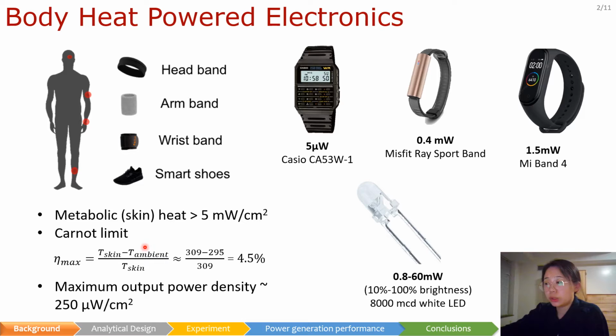According to Carnot's rule, the maximum efficiency is the ratio of the temperature difference between the reservoirs to the hot reservoir temperature. Therefore, we can estimate the maximum output power density of a device operating between the body temperature and ambient temperature to be about 250 microwatts per square centimeter. Given that the power demand of most IoT devices, as you can see examples on the right, is on the order of microwatts to milliwatts, we believe proper utilization of human metabolic heat should be enough to keep those electronics running.